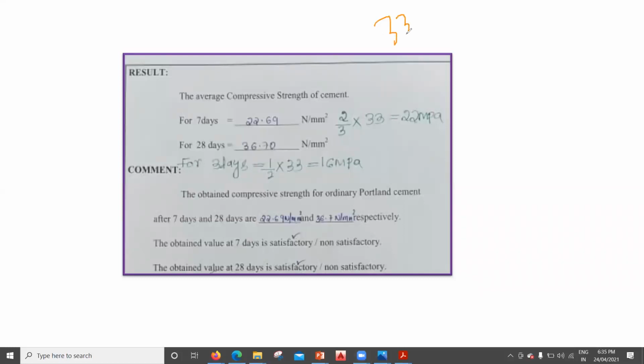That is 33 grade cement, we have 43 grade cement, and we have 53 grade cement. Right now, whatever I'm explaining is for 33 grade cement. Let us say at the end of 7 days, how much minimum strength do you need? We have a certain formula: 2/3 of the grade of the cement. Let us say I'm making use of 33 grade cement. What is 2/3 of that? If I do 2/3 of 33, I should get 22 megapascal or Newton per mm square.